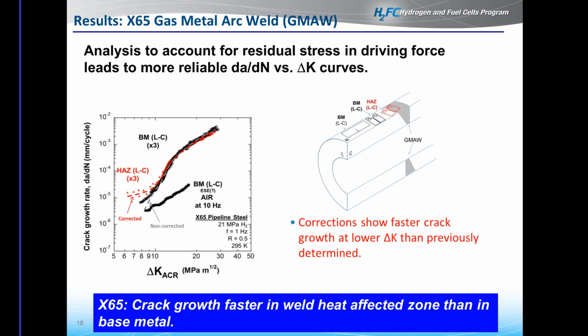The reason we're doing this is that a 1-inch thick weld pipe that is welded together is going to have different residual stresses than a 1/4-inch thick weld pipe or a 1/2-inch thick weld pipe. So the fatigue crack growth curves on the previous slide really don't differentiate that. It's just what that exact pipe is. And our ultimate goal is to characterize the intrinsic microstructural response to hydrogen. And we can't do that if we're masked by some residual stress. So this essentially represents a more accurate presentation of what's going on with heat affected zone microstructure as opposed to the base metal.